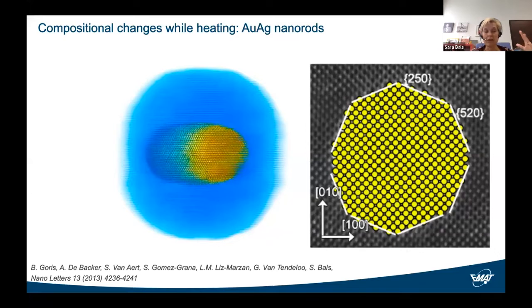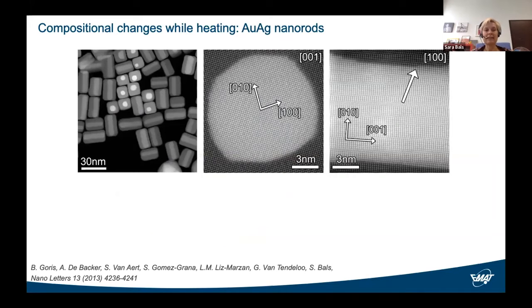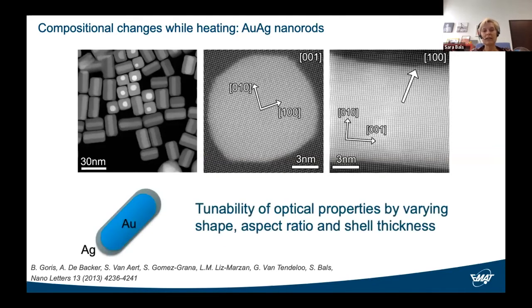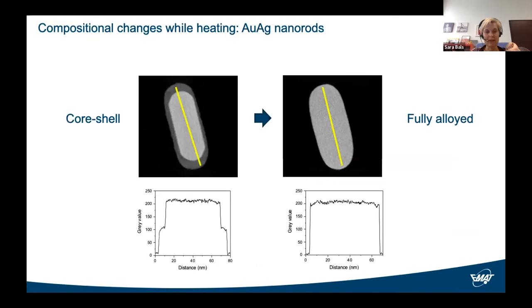Now, the reason for investigating the systems at higher temperature is that the tunability of the optical properties can be varied by changing the shape and the aspect ratio, but also because of the shell thickness. So it's important to understand if at higher temperature this core shell structure remains, yes or no. The answer is very simple. The core shell structure is not maintained, but very quickly a fully alloyed nanoparticle is formed.